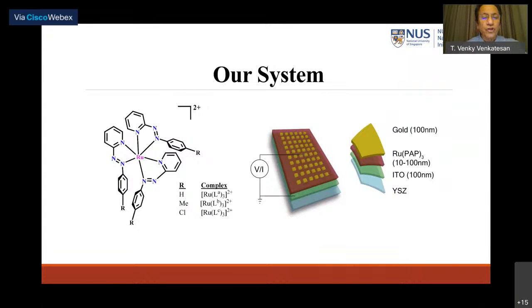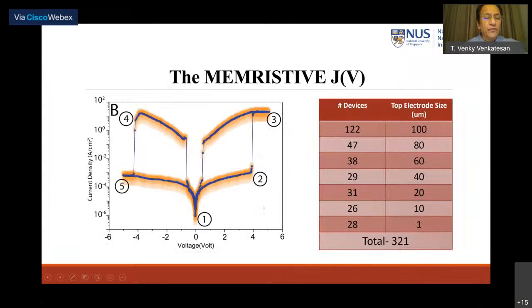And this is what you see. You see this very beautiful switching characteristic. This is the current density plotted as a function of the applied voltage. And what you see is the device goes from point 1 to point 2, switches to position 3. There's a hysteresis, it comes back down. And then when I go to the negative side, it switches immediately back and goes to position 4, then comes back down to position 5 and back.